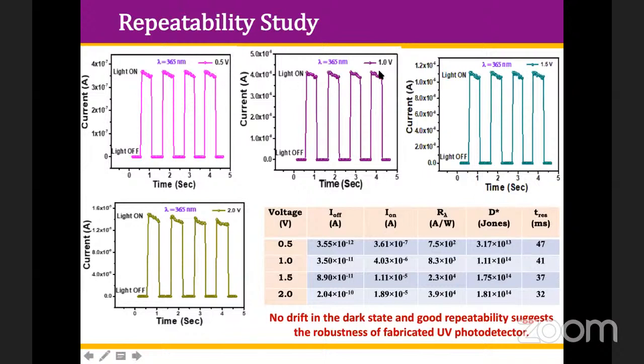Repeatability study has been done for the photo response, and you can see here with different bias, 0.5 volt we applied, then 1 volt, 1.5 volt, and 2 volt. In all the cases, the baseline remains the same. There is no drifting in the current, and repeatability is there. When light is on, the photo current is more, and when light is switched off, again it comes back to the original position. And with this repeatability, you can use the same photo detector a number of times.